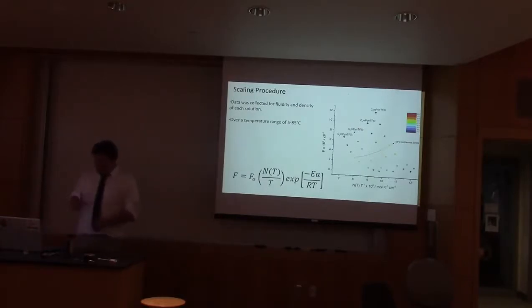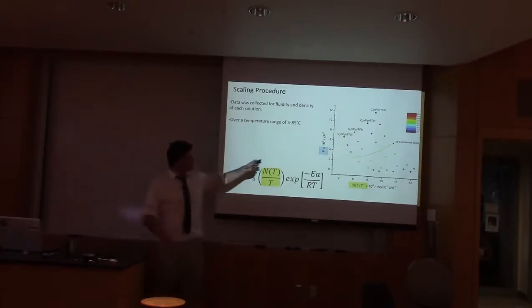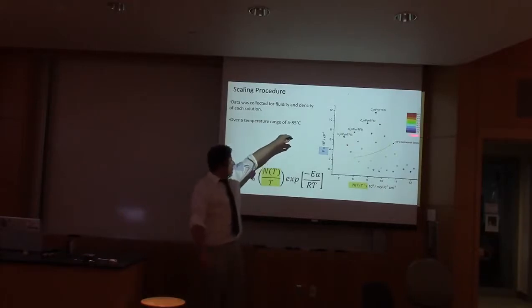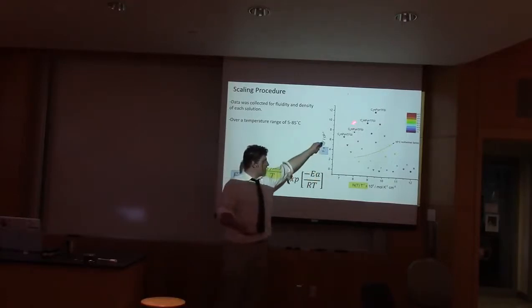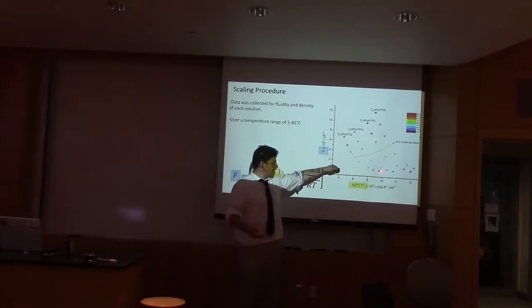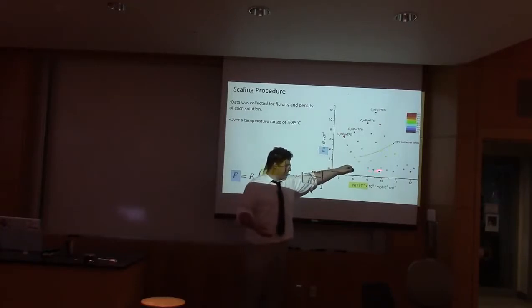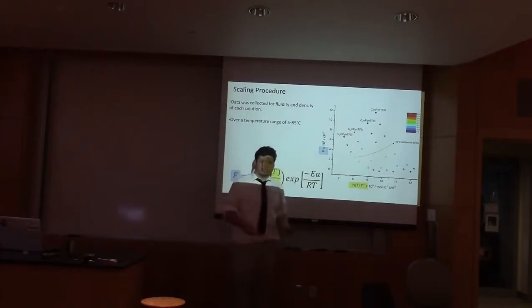Using this, we were able to collect data for all 4 room temperature ionic liquids doped with lithium salts. This specific plot shows the dipole density divided by temperature on the x-axis, and the fluidity, inverse viscosity, on the y-axis. On the right we have a temperature scale, where the darker colors correspond to lower temperature, 5 degrees Celsius, and as we get warmer we go up to 85 degrees Celsius. For each individual series, we take the temperature, the fluidity, and the density of the solution at each point. In that way, we are able to calculate the dipole density, which is the x-axis.